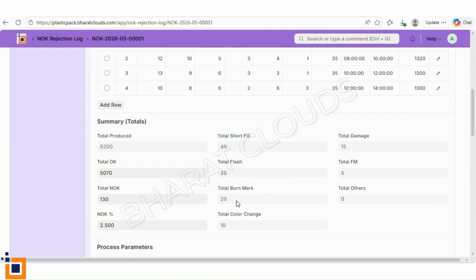20 burn marks. Trapped air isn't venting fast enough, or the material is degrading from too high temperature. 10 color changes. Probably from the previous batch's pigment still in the barrel during changeover. 15 damaged. Handling issues after ejection. 5 foreign material. Contamination in the hopper or the regrind mix. Each of these tells a different story. Each points to a different root cause. And the system has them all, shift by shift, machine by machine, mold by mold.